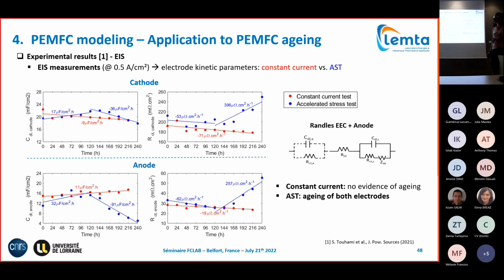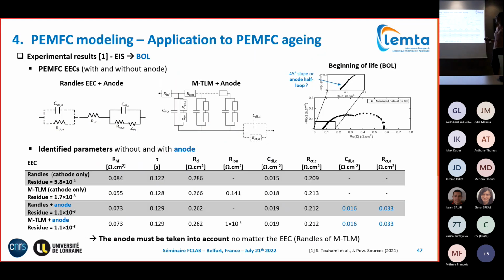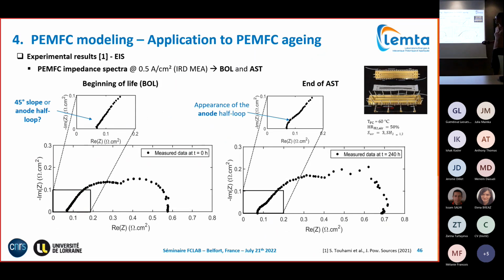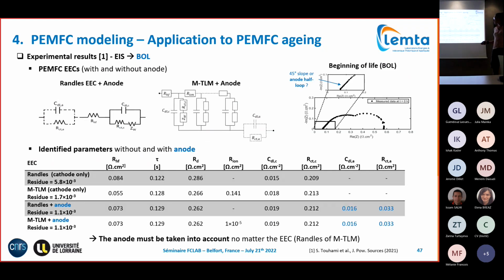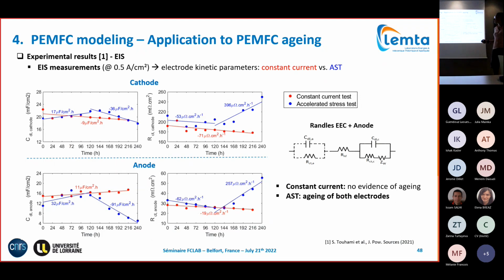It's really based on measured experimental data. And here, perhaps the lines you see, it's just a linear interpolation done for us. The dots are identified parameters that we identified by fitting all our measured spectra. From these measured spectra, we fit them and we identify parameters, and the identified parameters are these points. Here the lines are just a linear interpolation to have an idea of the aging, supposing that in 10 days it is more or less linear aging.